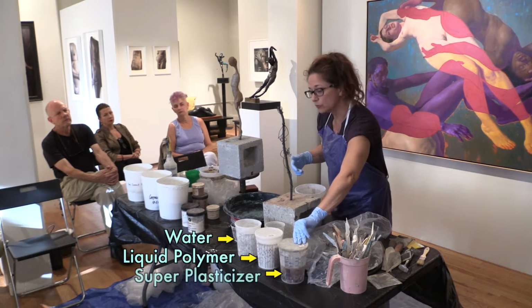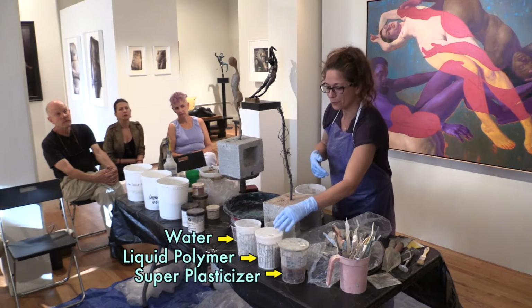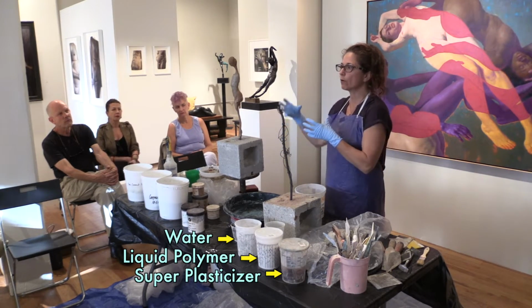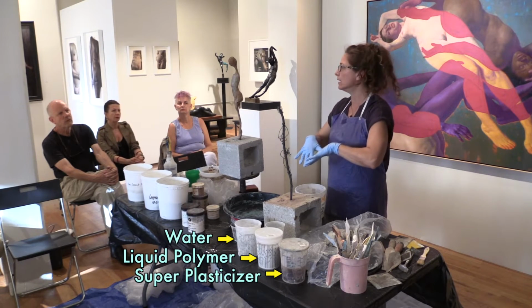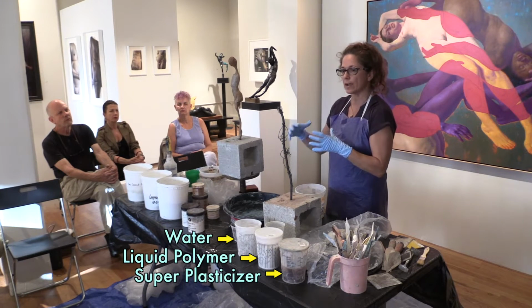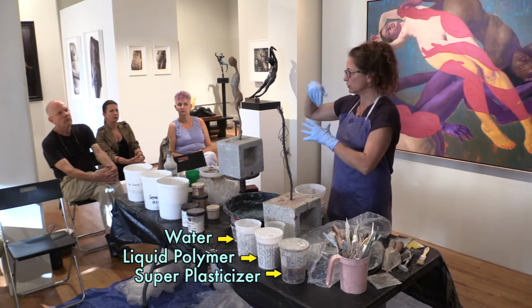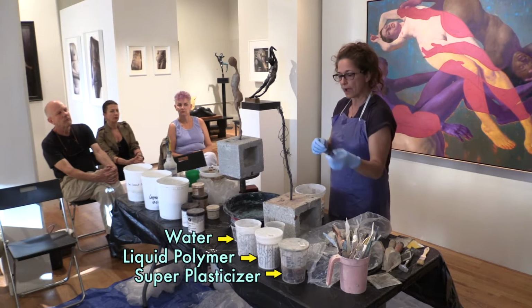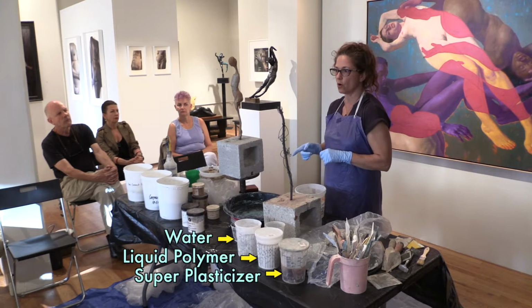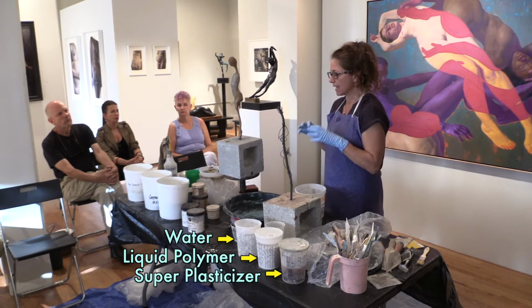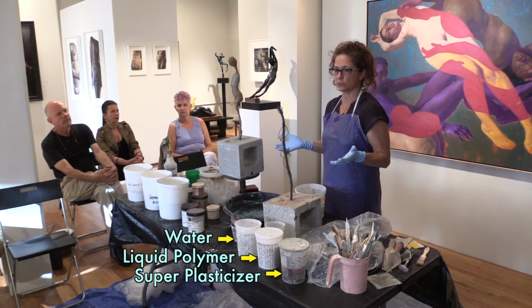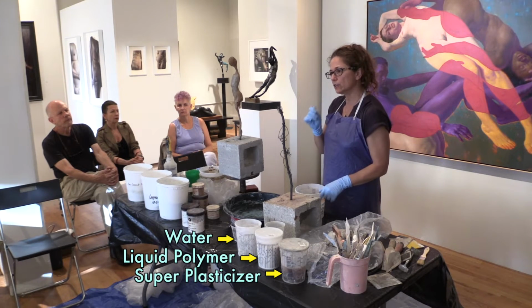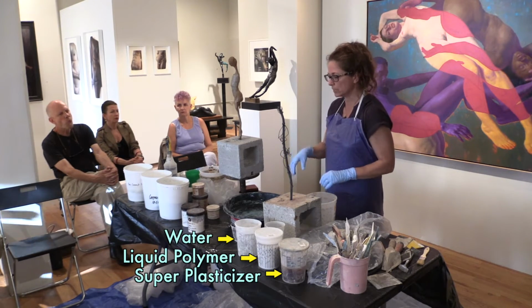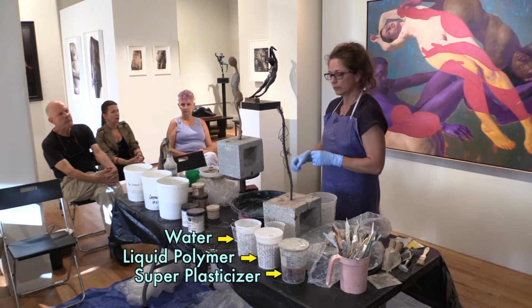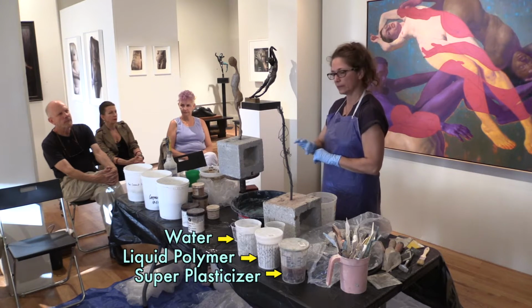And then I have here what's called super plasticizer, which is a step further than polymers. This is usually used when you want to pour it into a form and you want it to fill. It has a consolidating effect. So if you have a really dry mixture and you add some of this, it liquefies it so you can pour it in and it gets into all these little details. I'll use it here because I don't want to add too much water. If I add too much water, the excess water simply rises to the top and weakens my resulting material. So I don't want to do that. I know how much water I can add to a specific mix and what it needs to look like. And if I need it to be a little wetter, I just take a few drops of that, and I mean drops, and it's exactly the way I need to work it.